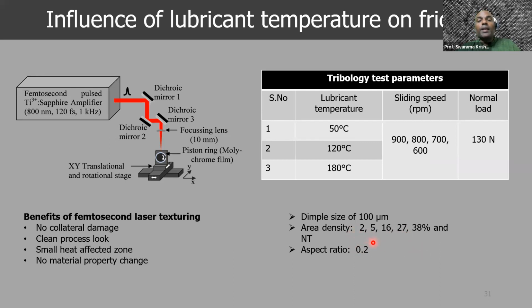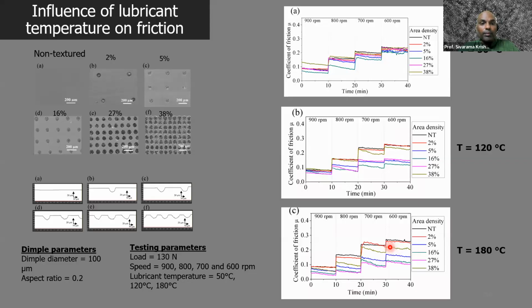The goal of this study was to look at the effect of these tribological parameters as a function of the density of the patterns on these samples, which will become very clear in this view graph. On the top left quadrant of this slide, you see going from A, B, C to F, increasing areal densities of dimpled patterns on this test piece, and we measured the coefficient of friction at different lubricant temperatures, going from 50 to 180 C at various different speeds. In all these cases, we find that the higher the groove density, the better the tribological performance, as one would expect, and that this is not critically dependent upon the lubricant temperature. We wouldn't want it to depend strongly on lubricant temperature.